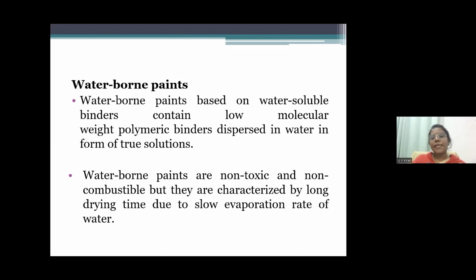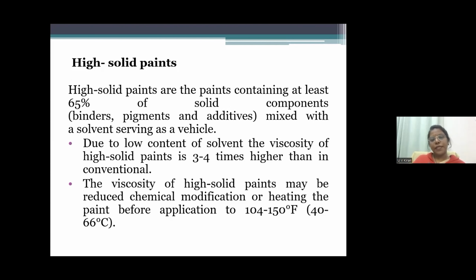Then water-borne paints have water-soluble binders. They contain low molecular weight polymeric binders dispersed in water, and it forms a true solution. They're non-toxic, non-combustible, but they're characterized by long drying time due to their slow evaporation rate.